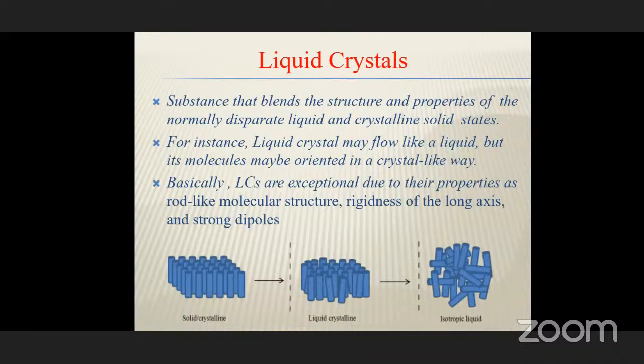So we can say that the distinguishing characteristic of the liquid crystal state is the tendency of the molecules to point along a common axis called the director. This is in contrast to the liquid phase, where we have no intrinsic order, but in the solid state, molecules are highly ordered and have little translational freedom. The characteristic orientational order of the liquid crystal state is between the solid and liquid phases. This is the origin of the mesogenic state.